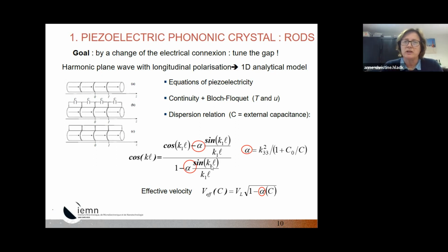In this dispersion relation, you have an additional term, alpha, which is related to the capacitance that you put at the extremity of the rod. If all the electrodes are in open circuit, in that case alpha is equal to 0, and you have exactly the dispersion relation for a homogeneous material. As soon as you put an external capacitance, or if it is short-circuited, then, due to the alpha term, you will change the dispersion relation. In the large wavelength limit, you can also find the effective velocity like this one.